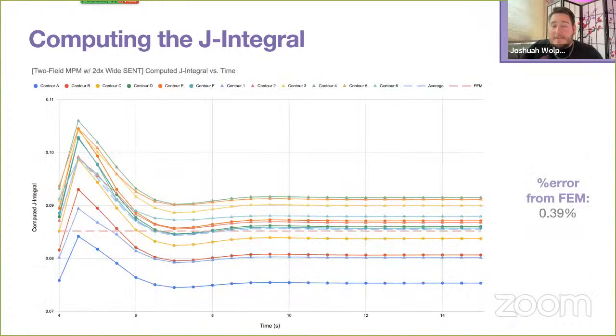So here we're plotting for each contour the computed J integral value over time using our two-field MPM approach. And since we're using explicit MPM, we slowly ramp up the traction for the first 4 seconds and then let it oscillate out and come to rest for another 11 seconds. And you can see in the dashed blue line that the average J integral value over time converges very closely to the value we got in FEM, showing yet another successful application of this damage gradient partition two-field MPM.